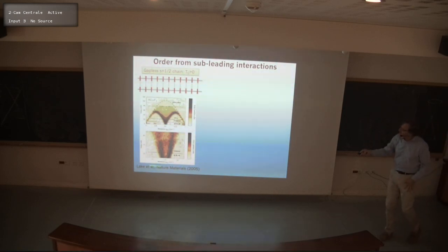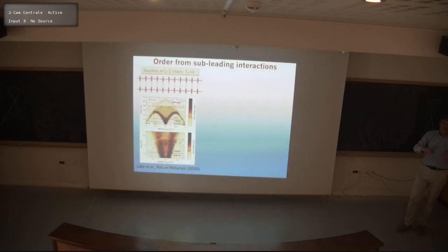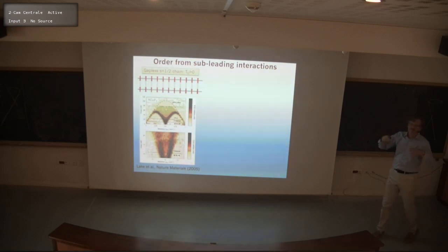And in the case of the spin half chain, you have a system which actually is in a kind of critical state. And it has to do, in a sense, with the fluctuating nature of the valence bond coverage. The resonating valence bond state, if you just apply a tiny little staggered field, will respond very strongly. You could also say that it's because of it being gapless that it has this very strong response to the symmetry breaking field. So it means that if you put two spin half chains next to each other, both of them are just on the verge of forming an antiferromagnet, and any weak interaction will eventually, at sufficiently low temperature, cause the system to go into an ordered state.